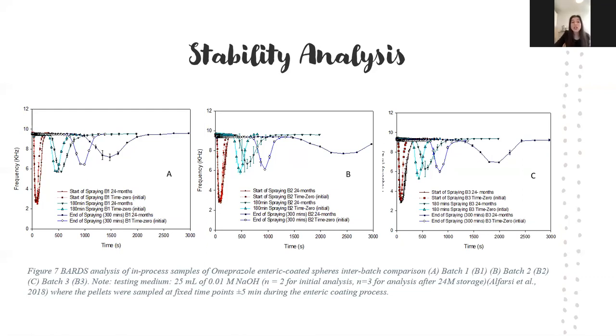Figure 7A shows the BARDS data for batch 1, B for batch 2, and C for batch 3. The dissolution behaviour remains similar to the previous analysis, with insignificant error to the dissolution. However, the lag time of all samples has increased in the last 24 months. A trend is observed whereby the thickest coating demonstrates the most considerable change of sample behaviour.